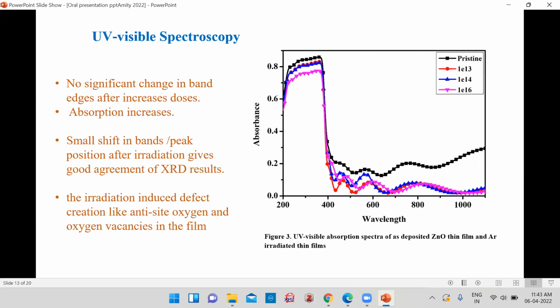This is the UV visible spectra, in which we can see that in the pristine film we have observed the absorption band, but after irradiation the absorption bands get sharp. It reveals that the absorption increases. There is no significant change in the band edges. There is a very small shift, which gives good agreement with the XRD results. The ion irradiation induces defect creation.